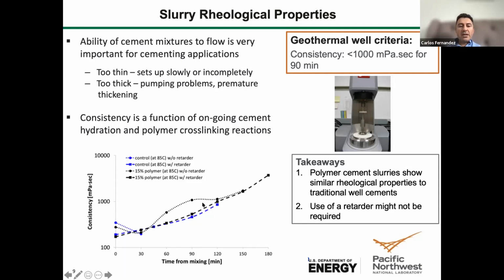The polymer in 2 of the 3 formulations that we are going to present here shows retarded effects. So if you measure the consistency over time as the material hardens, the consistency increases. In the case of a control, unmodified material without a retarder, you will have in less than 30 minutes a complete boost of consistency, and the material is no longer workable. So you need a retarder. In the case of polymer cements, and we're talking about 15%, but in some cases we go as low as 5% based on dry cement, you don't need a retarder.